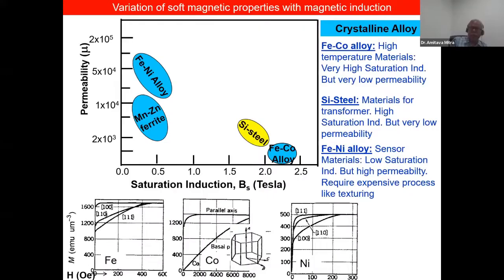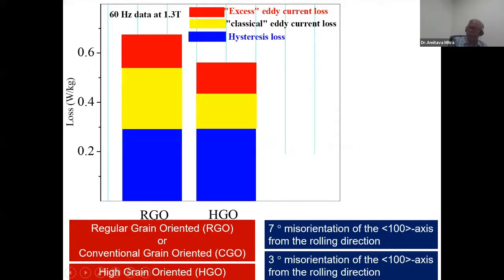So the existing material, silicon steel, as I told you, makes up the majority of magnetic materials. It has two varieties: regular grain oriented and high grain oriented. The most important property is the loss, which means the area of the hysteresis loop. You can see this is around 0.65 watt for the regular grain oriented material, and it has three components.